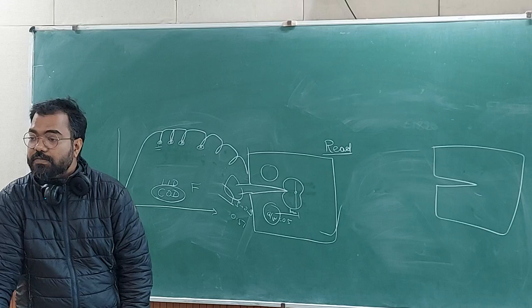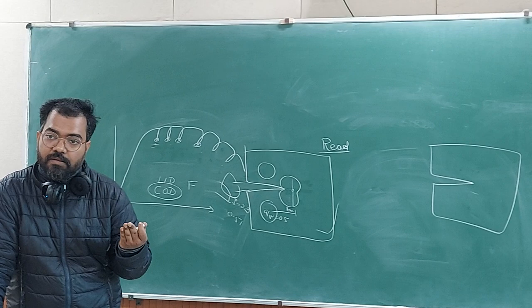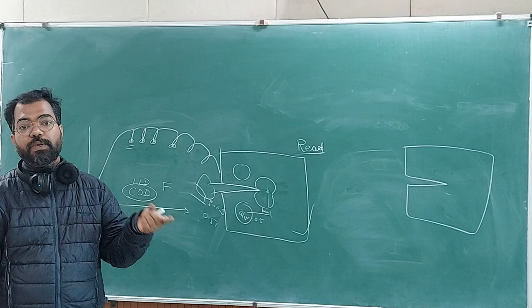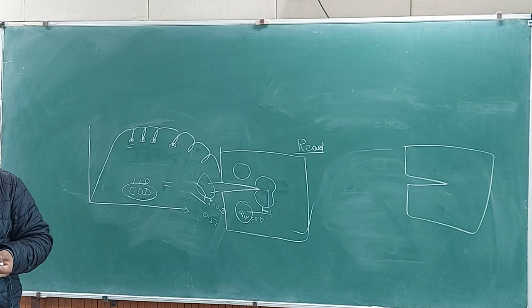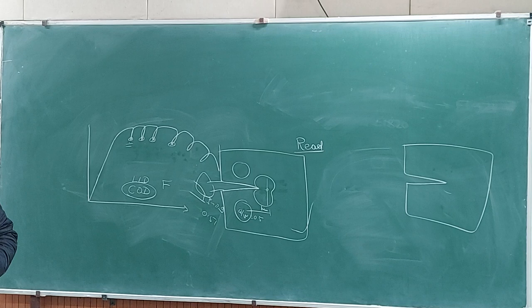The reason for fatigue is this: we break it in fatigue so that we can clearly see the difference between the crack growth which has happened during the monotonic loading and in fatigue. So people before this used to do it by heat tinting. They will stop the test somewhere and then they will put a furnace around the sample and they will just heat it. Okay, there is some temperature where you are supposed to heat it for certain duration.